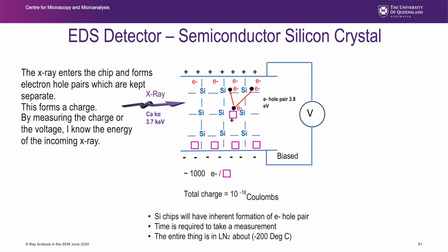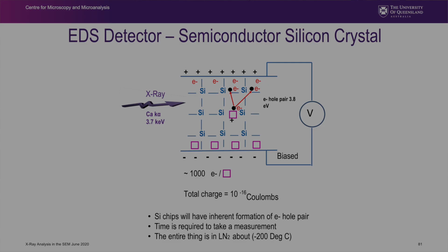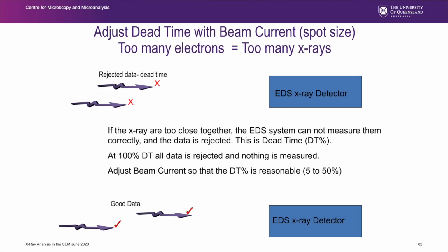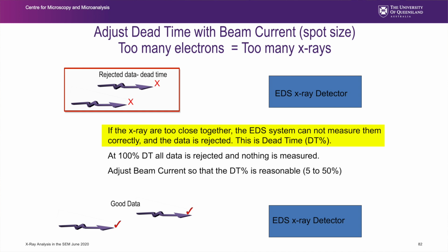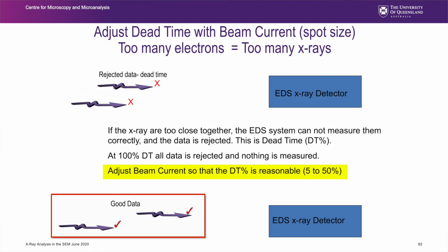We've got to do 2 things. While the X-ray is forming electron hole pairs, we can't have any other X-rays come in. It destroys the quality of the measurement. And we've talked about that earlier. It's called the dead time. 2 X-rays come together, we get rid of both of them, reset the crystal to ground state, start again. So when the dead time is too high, 100%, there are too many X-rays. We adjust the spot size, the number of electrons, to get a dead time somewhere between 5 and 50%. We want well-spaced X-rays, 1 X-ray at a time.